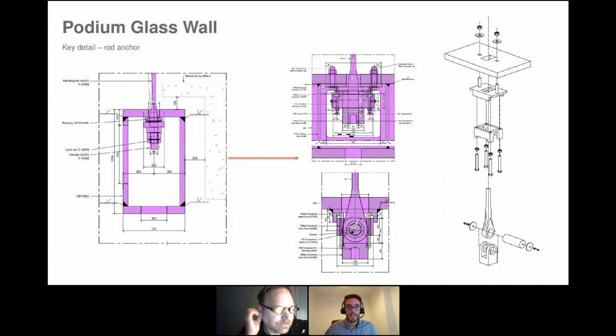Another key detail is clearly the anchoring of the rod to the beam. What we started with was a relatively simple detail. We were assuming this square, rectangular rod to then turn into a circular one through CNC machining, and then having a spherical bearing and threaded nut to ensure that the rod was secured against the beam. Clearly, we had to provide openings on the side of the beam for inspection and on the bottom of the beam for pretensioning. Unfortunately, there were a few problems in getting the approval from the building department in Hong Kong.